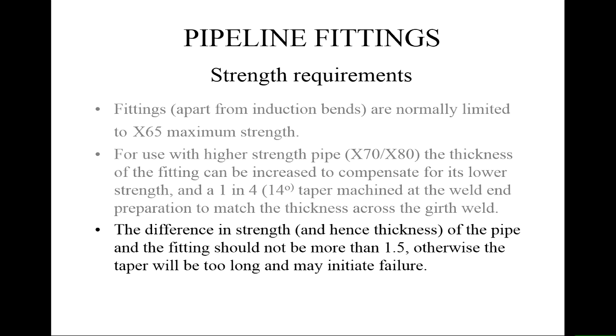Generally we say that this difference in thickness shouldn't be more than 1.5, otherwise you'll have a very, very long taper, and that will be very bad news. Failure will occur in the taper, and we don't want that.